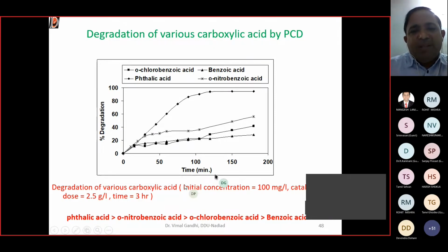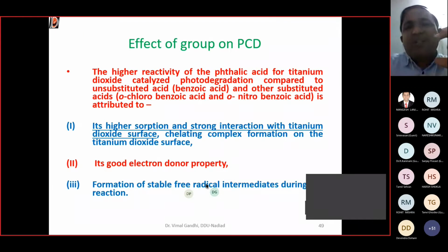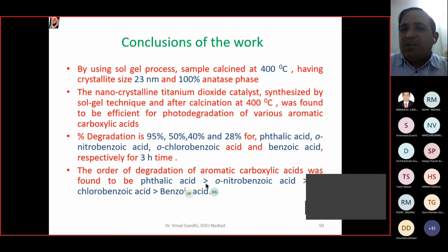But the important point is that the aromatic carboxylic acid that is adsorbed more on the surface of the catalytic site gives the best result, and the least adsorbed one gives the least result. So that we know in catalysis also, right? So we tried to find the effect of that group on photocatalytic degradation, and we found that higher sorption and strong interaction with the titanium dioxide surface in the case of phthalic acid gives the best result, while benzoic acid gives the least result. Along with this, we proposed the mechanism also, but I don't want to cover that here. Degradation pathways in 4 cases.